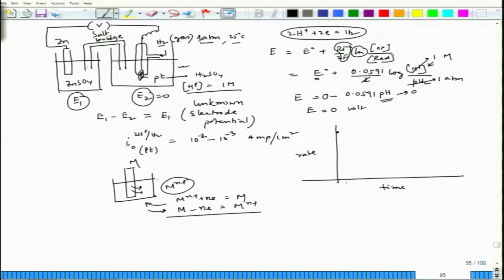Now, let us say initially the reduction reaction would be very high, because we already have the presence of Mn+. Depending on its reduction potential, Mn+ would try to reduce and form M, and as this reaction starts, the reverse reaction would also start, but they will be sluggish in the beginning, and as time passes the rate will pick up. So, the rate of Mn+ plus Ne going to M initially would be very high, because Mn+ ions are already present, and the reverse reaction, M going to Mn+, would be less initially, because the Mn+ ion would get reduced first, and then the metal would release electrons and form metal ions.